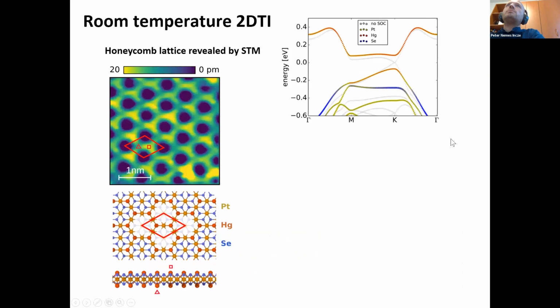Now, if you zoom in with the STM, almost immediately when measuring in the conduction band of this material, you can see this honeycomb lattice appearing. It's not quite the honeycomb lattice of graphene, because it has a so-called sublattice symmetry broken structure, whereby one of the sublattices, shown by the rectangle here, and the other, shown by the triangle, are not of the same height. This is quite expected, because if you look at it from the side, one of these sublattices is on the bottom of the layer, and the other is on the top of the layer. So this results in this sublattice symmetry broken STM image.